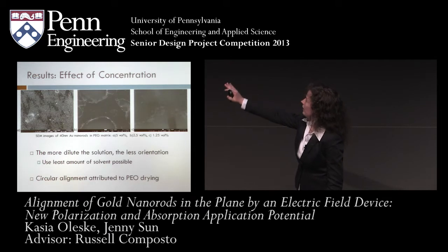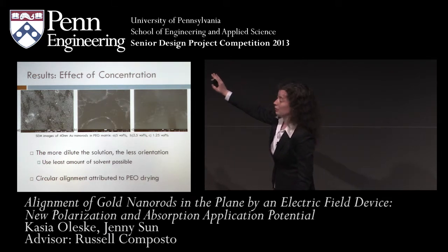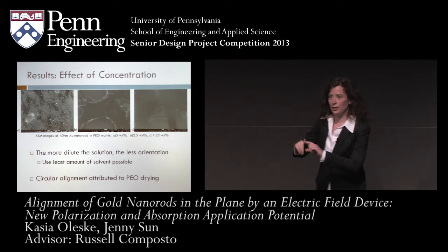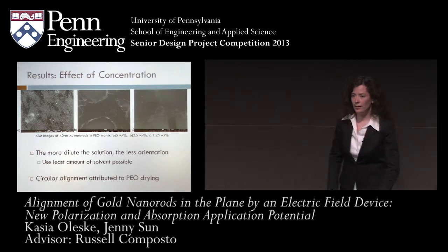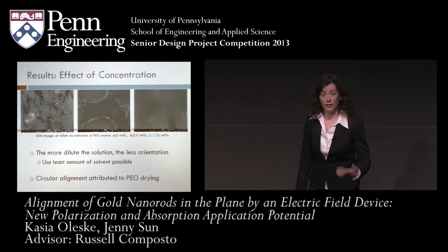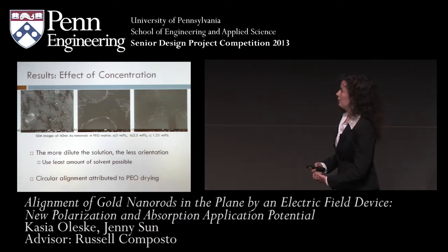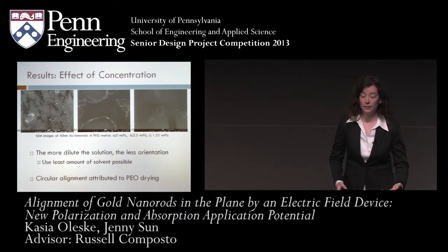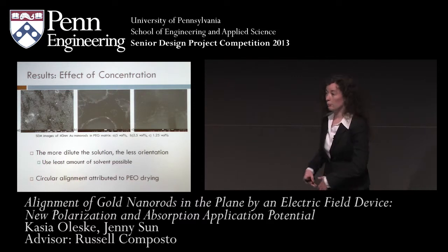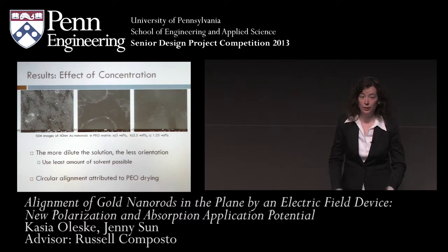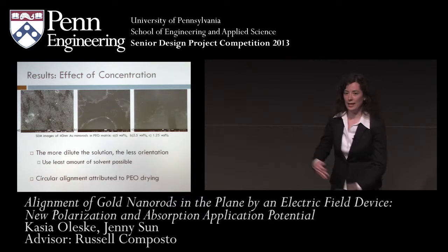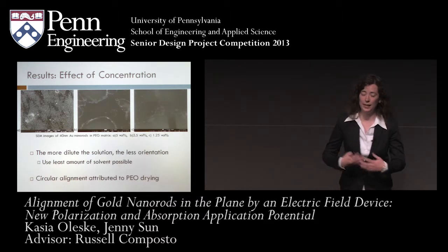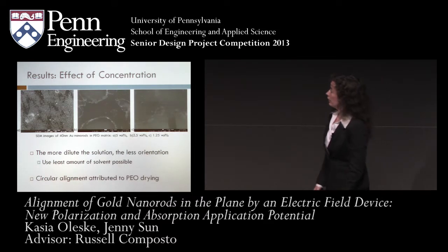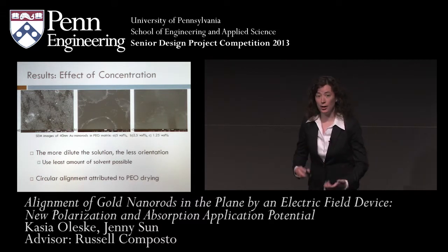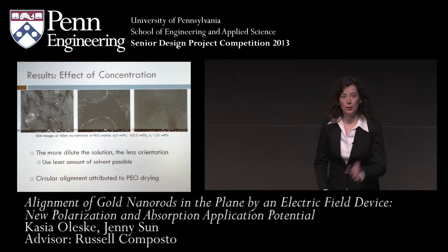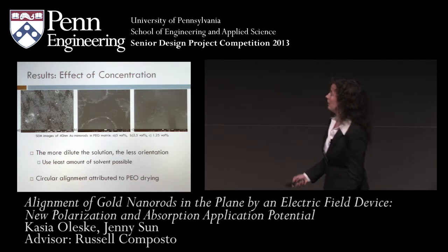You can also see that in the lower concentrations, you see the circular orientation. This is attributed to the polyethylene oxide in the solution because these form circular micelles in 3 dimensions. But when PEO dries, if there's any residue, the gold nanorods will want to orient in circles instead of being aligned in the electric field. So in the future, we'd prefer to use either no solvent or minimal solvent in order to get increased alignment.